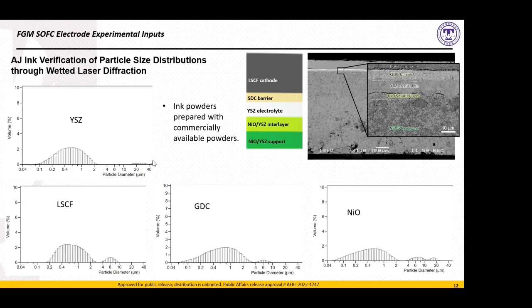sizes. The first thing that we did was we verified the particle size distributions of our ink through wetted laser diffraction here at Tennessee Tech. And here you see a schematic of a typical SOFC. The cathode will be formed of LSCF, which is a lanthanum with a strontium doping and cobalt ferrite material. You also have a samarium doped ceria, a yttria stabilized zirconia electrolyte, and a nickel oxide YSZ interlayer. And then upon operation, this nickel oxide will be reduced to nickel.